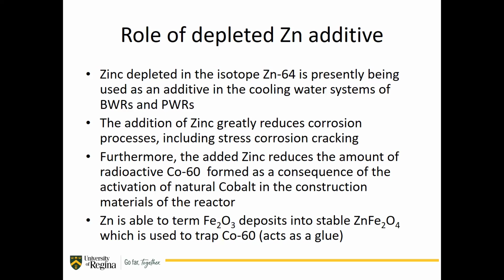One of the ways in which this is controlled is through the addition of zinc. Zinc in the form of isotope 64 specifically, as zinc oxide, can be added to the actual BWR. In doing so, it incentivizes the formation of these zinc iron deposits, these spinel deposits, and those can act as glue to hold the cobalt-60 in place within the actual corrosion products. I don't actually know if cobalt-60 is sitting within the spinel structure or the hematite, but regardless, it basically hardens everything within the pressure vessel, and thus you're not worried about it getting into the turbine hull.